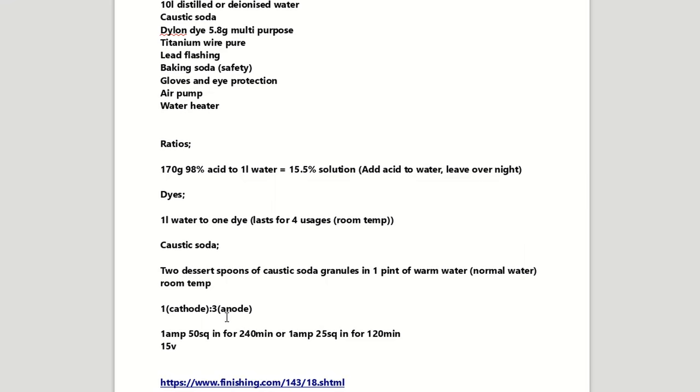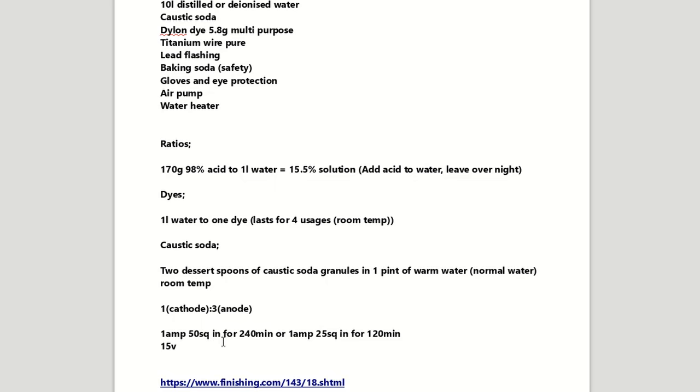There's other formulas and it's kind of like the other way around but I think that's more for using other methods of anodising not the 720. Like I say I'm a bit vague on this whole anodising thing. I've tried to get my head around it as much as possible. I'm not going to be doing it professionally or anything like that. It's just something I've always wanted to dip my hands in and try. So with the 720 solution, 720 ratio method, it's kind of like one amp per 50 square inches for 240 minutes. If you had a lesser square inch piece to be anodised you could go one amp for 25 square inches for 120 minutes. So you can half that.